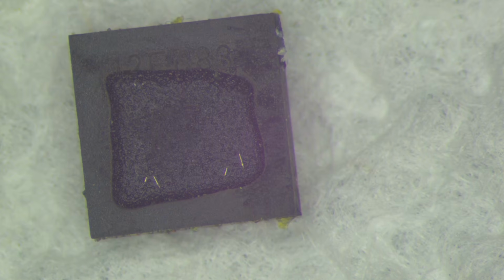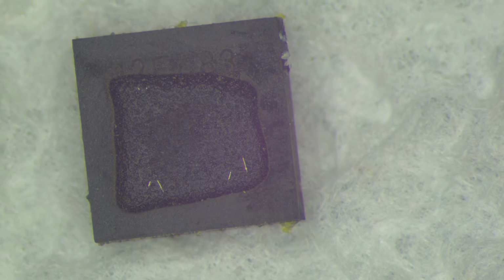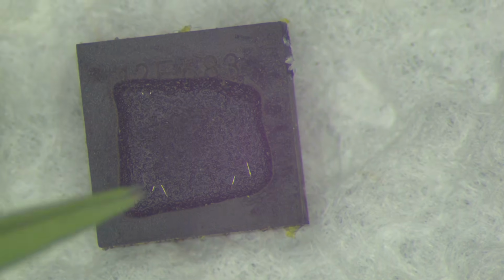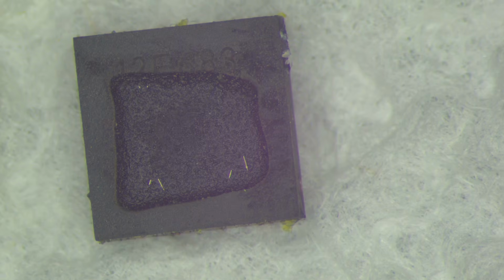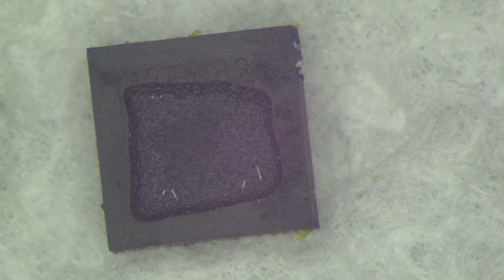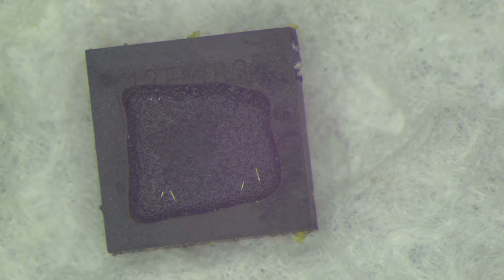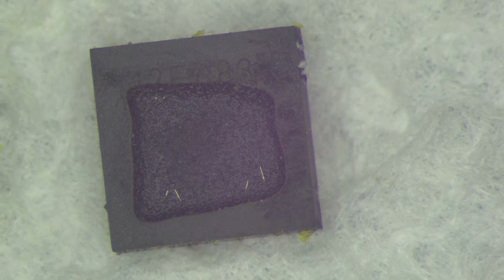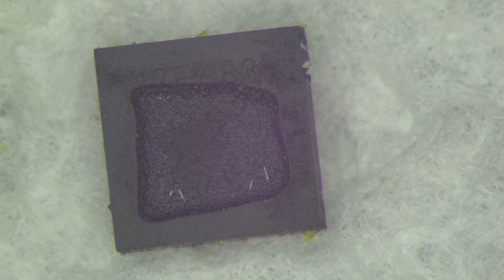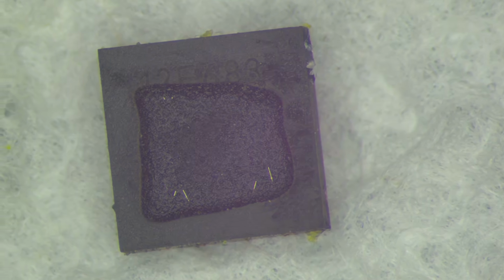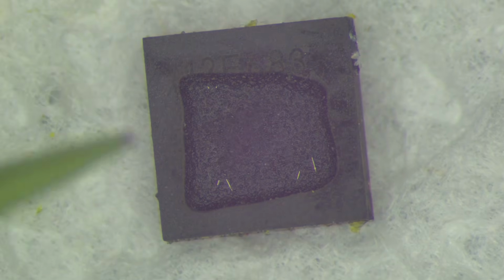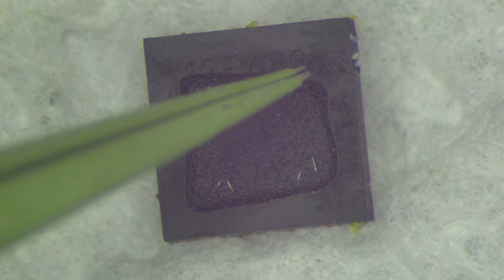And so at this point, I unmounted the sample from the holder and decided to take a look at how the process was going. We can see we've got bond wires exposed on 3 corners, but the other reason is that although the mask had not degraded to the point that I was worried about it undercutting, there is one corner at the top right here where it looks like the mask was actually a little bit too tight and is covering a corner of the die, and so I decided I was going to take it off and make the mask a little bit looser.